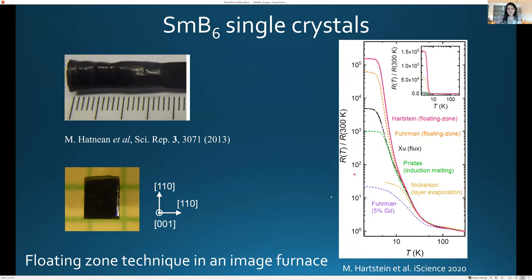grown crystals at the group of Warwick. And so why this is important is that this is not grown out of a metallic flux. So there's several very, very good crystal growths that have been done using metallic flux. But if you are to grow an insulator especially, you do run the risk that any contamination by metallic flux will give you metallic inclusions that you could confuse with that coming from the bulk of the material.